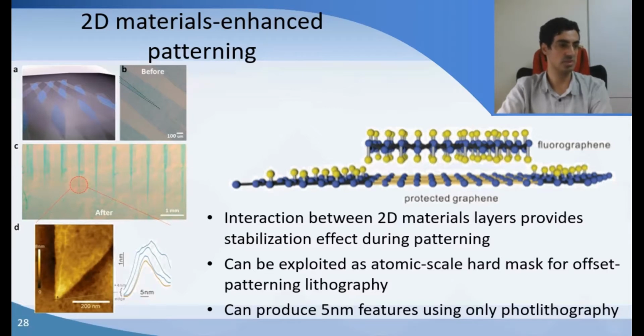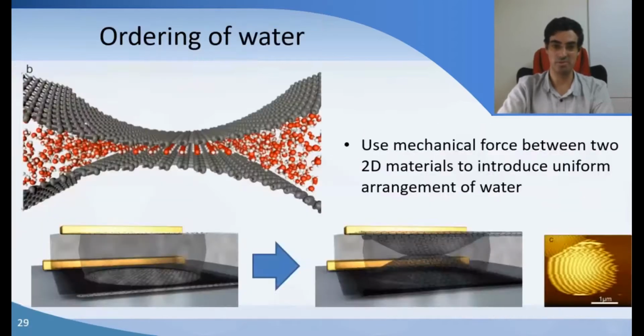And so we've used that to produce features that are 5 nanometers in size. This is done by simple optical large-scale lithography, but we can generate this with very high throughput and very high resolution. The last part that I wanted to describe is a strange effect that we're seeing when we're ordering water on or in between 2D materials.